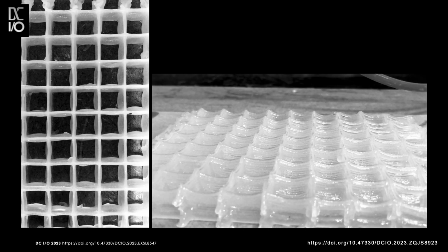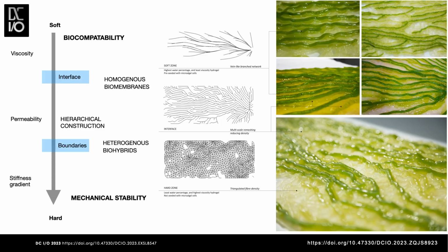And we did manage to actually 3D print, and what you're seeing here currently on the screen is a 30 centimeter long acrylic panel, which has been 3D printed down to a resolution of 2 mm with the hydrogel, and there are about 9 to 12 layers that were extruded at this resolution. Our next stage was obviously to embed these layers, but we simultaneously wanted to increase the scale from 30 centimeter to about 1 meter. And we went on to fabricate these panels, these fibrous-like panels, keeping in mind the viscosity of the material, the microalgal demands, the requirements for the microalgae.